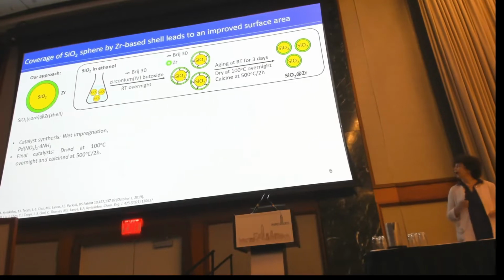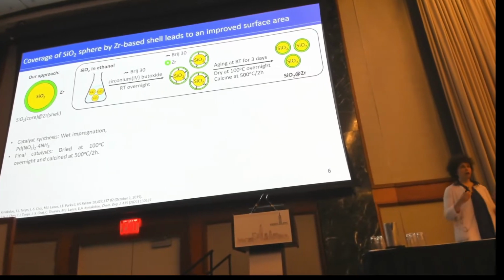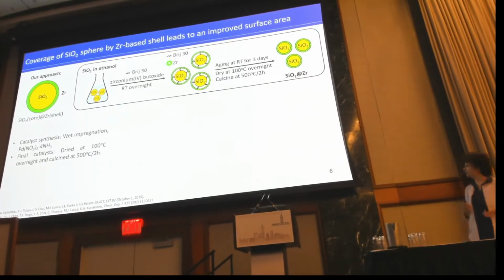And of course, after that, we wanted to add the precious metal, which in this case is palladium. Palladium is added with wet impregnation, the final catalyst. After the palladium impregnation, it is dried at 100 degrees C and calcined at 500 degrees C for 2 hours.